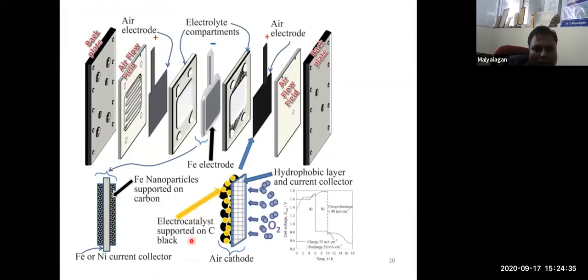When you look at the cell design, as I said, you need a flow field for oxygen airflow. This is a flow field for the air electrode, this is your catalyst layer, and this is the electrolyte compartment. If you use iron, you can use an iron electrode. If you use zinc, you can use zinc foil. So this design is quite similar for all air batteries. The development should take place in these air electrodes. This is what is much more needed. You need a better catalyst to develop the air electrode, the air cathode.